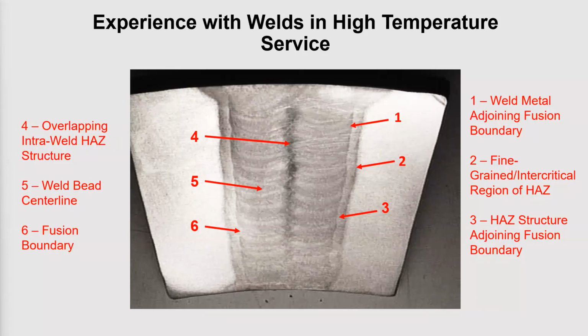damage due to operating conditions are, first of all, the weld metal immediately adjoining the fusion boundary. Another area that very commonly, and this relates to the type 4 region, is the fine grain intercritical region of the heat affected zone out at the edge, number 2. Number 3 would be in the heat affected zone structure, but more closely located toward the fusion boundary. So in what oftentimes would be called the coarse grain region of the heat affected zone.